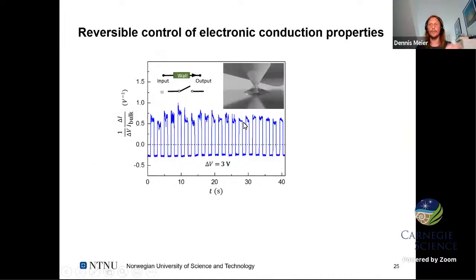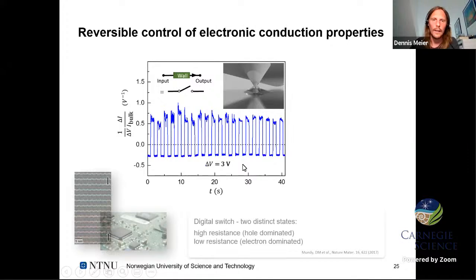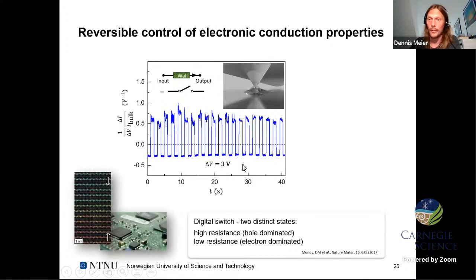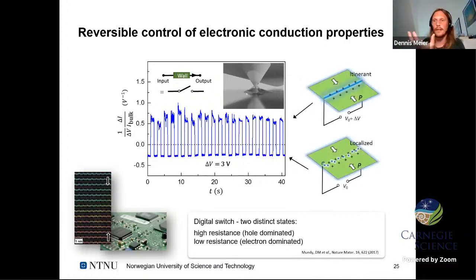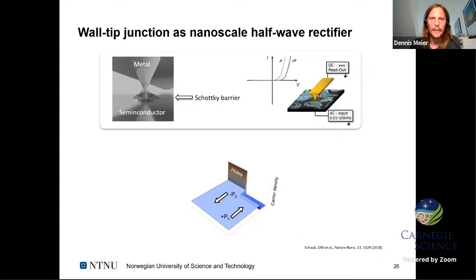What's really nice is we can also do that sitting just with the tip locally on a domain wall, and then going with a voltage up and down, and repeatedly switch between insulating and conducting states relative to the surrounding bulk. Two-state digital switch is the behavior we are mimicking here. And the idea is that we have these electrons which are sitting at the position of the wall. They are in a localized state at low voltages, and when I have a high enough driving voltage, they become itinerant.